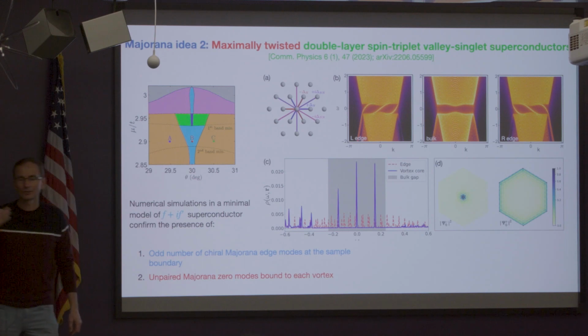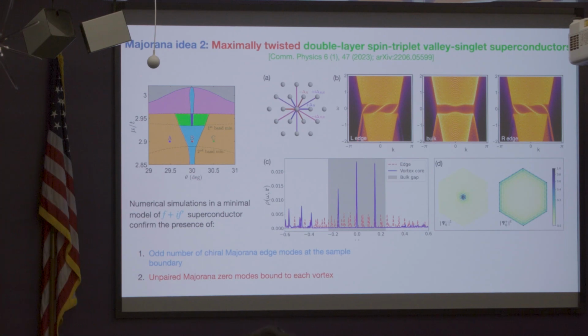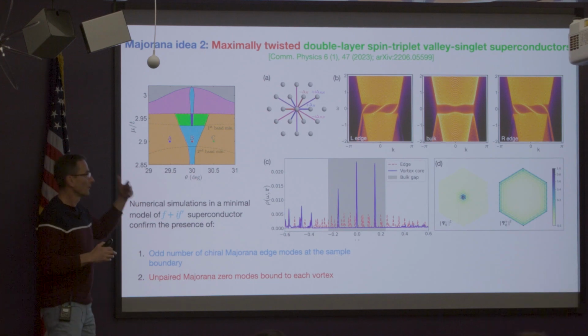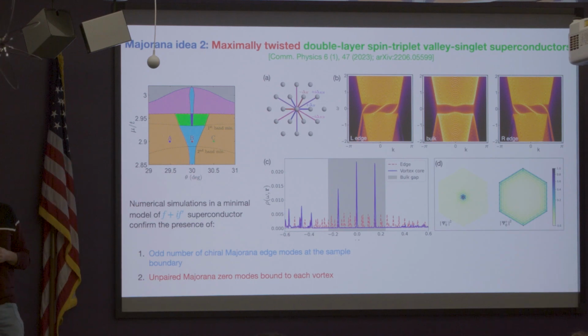So this is a higher angular momentum analog of a two-dimensional p plus ip superconductor, which potentially could be created by this twist angle engineering. Is it a realistic proposal? Well, you know, you have to ask people like Jane. I don't know. But in principle, at least from this spin singlet valley triplet superconductor that we think exists in these materials, by twist angle engineering, one should be able to get that near 30-degree twist, and by tuning the chemical potential. Okay, so this is Majorana idea number 2.